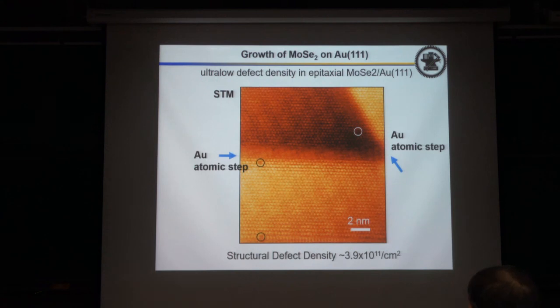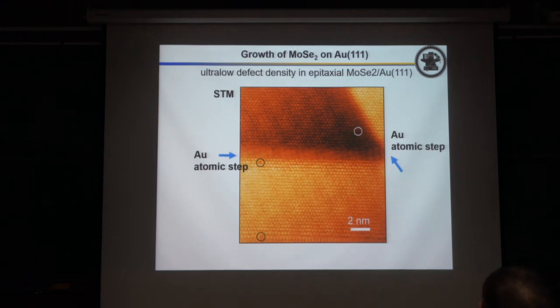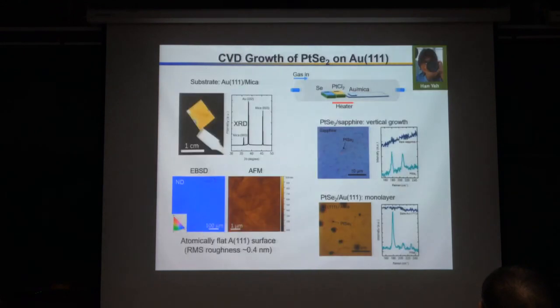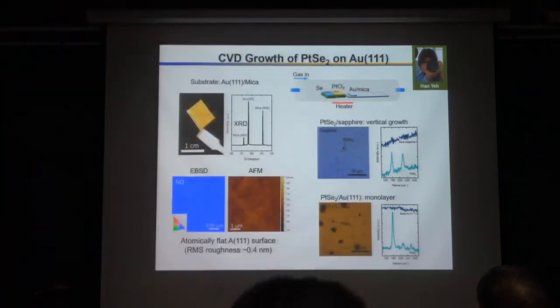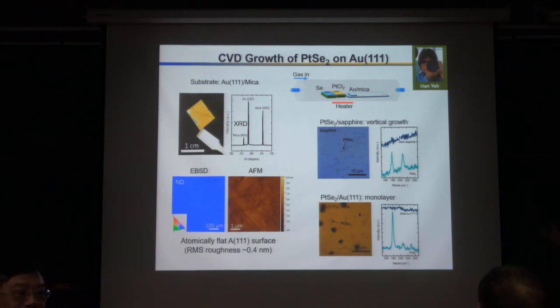And the second question is about platinum diselenide. You calculated that 30 years ago, right? When I was a student, I was wondering, molybdenum disulfide and these direct band gap materials have a lot of interesting things. What's the advantage of platinum diselenide? Why do you want to grow it? For platinum diselenide, the key is that they have very strong band gap modulation with the layer thickness. But I guess it's not direct band gap. Yes, but for electronics, it has nothing to do with direct or indirect. For silicon it's also indirect. So it's a very good choice.